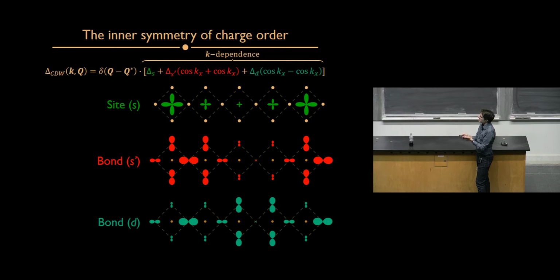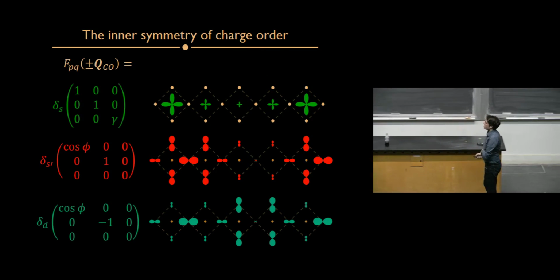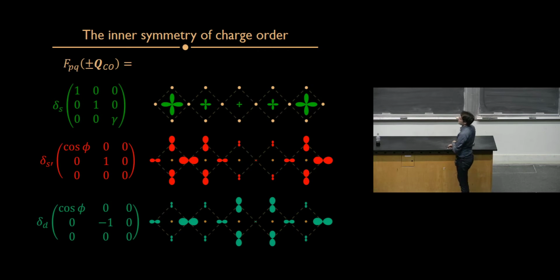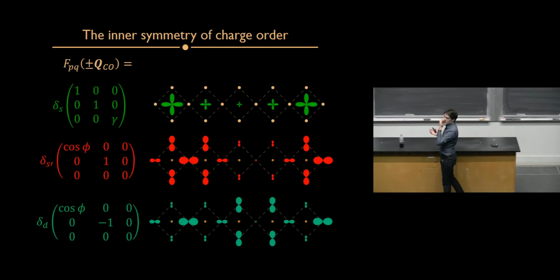In the D-wave bond type of order, then they're out of phase. So when it's maximum on the oxygen 2px, minimum on oxygen 2py, and then it oscillates back and forth, right? It goes minimum on 2px, maximum on 2py, and it oscillates back and forth as a function of the lattice position. Turns out you can map this onto a quantity which in resonant scattering we call the